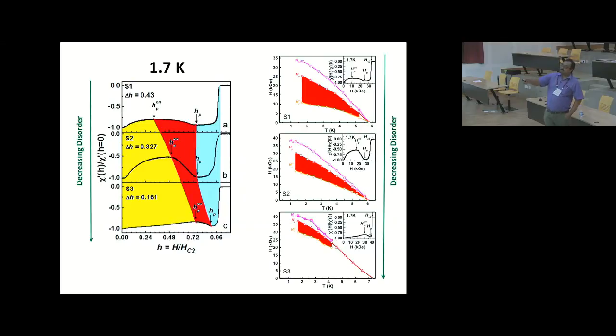You can also see the same thing in the phase diagram, where you see that this orientational glass shrinks as I go to cleaner crystals. So I think this gives us an indication that what we are seeing is essentially driven by the random pinning landscape.